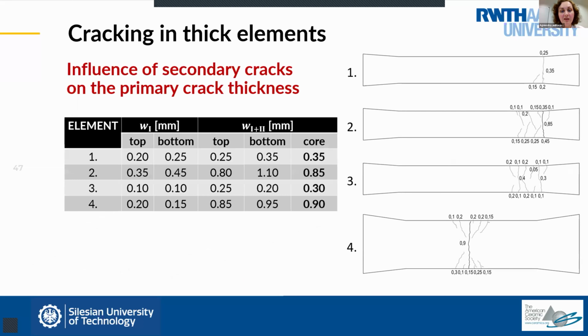First of all, this research confirmed this cracking pattern. So with increasing thickness, it is harder to produce another through crack, but the primary cracks are accompanied by secondary cracks, and these secondary cracks have very important meaning, in a sense that they are compensating the width of the crack. What does it mean? It means that if we look at the width of only the primary crack, then it is relatively small.